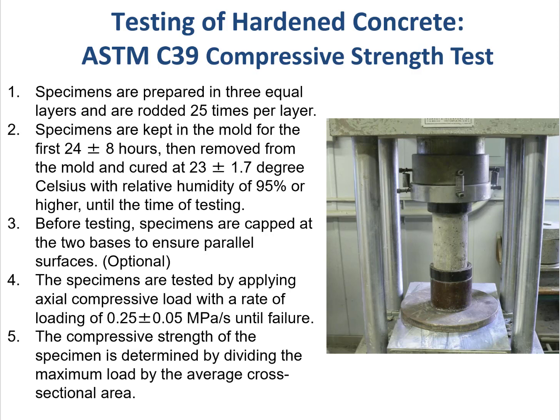This step is optional. The specimens are then tested by applying axial compressive load with a loading rate of about 0.25 plus or minus 0.05 MPa per second until failure. Finally, the compressive strength of the specimen is determined by dividing the maximum load by the average cross-sectional area.